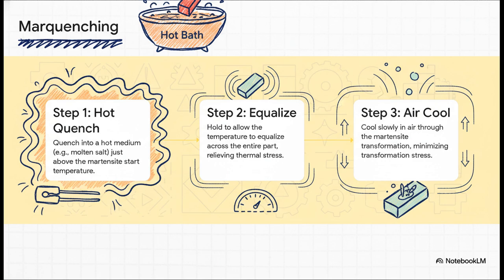Instead of just one violent plunge, the process is actually interrupted. First, you quench the part into a hot bath of, say, molten salt, and you pause it right about the temperature where that stressful expansion begins. Then you hold it there. This lets the temperature even out from the core all the way to the surface. It lets all that thermal stress relax before the transformation stress kicks in. It's brilliant. Then, and only then, you cool it slowly through that final phase.